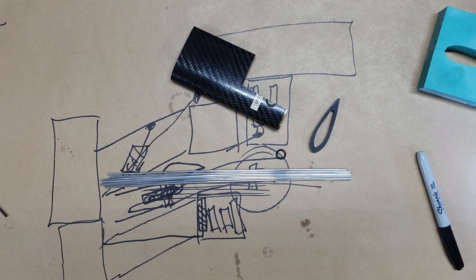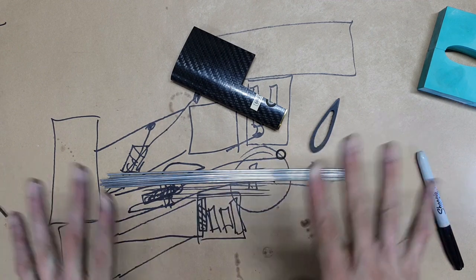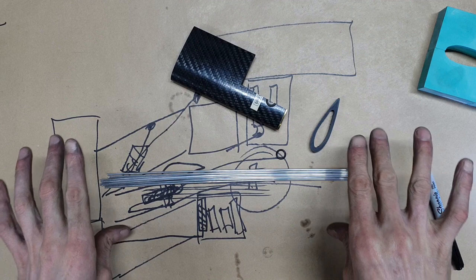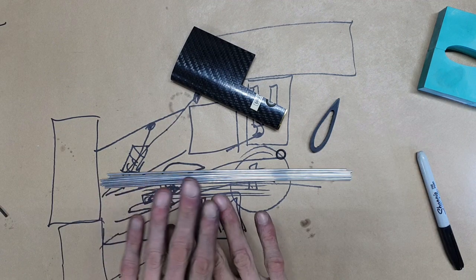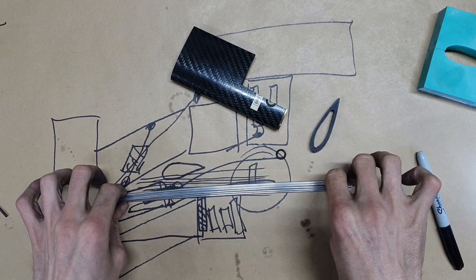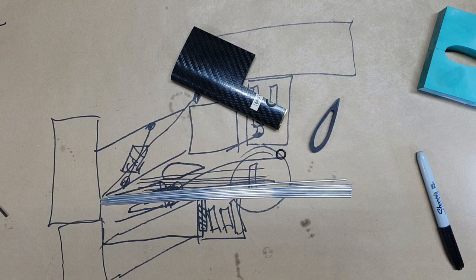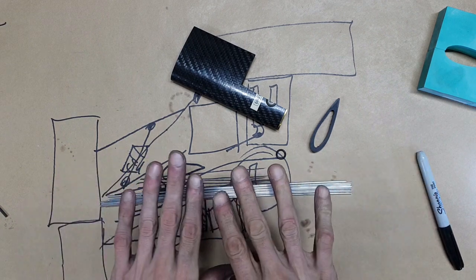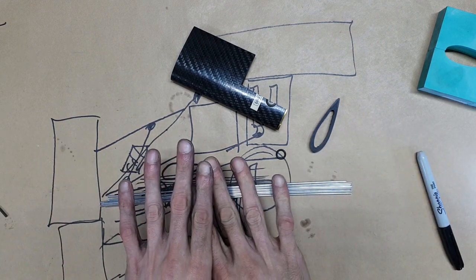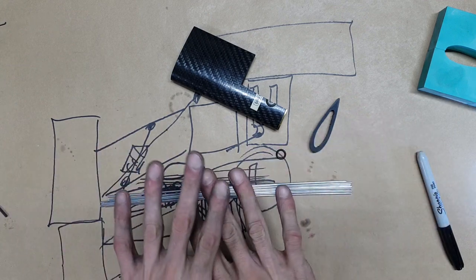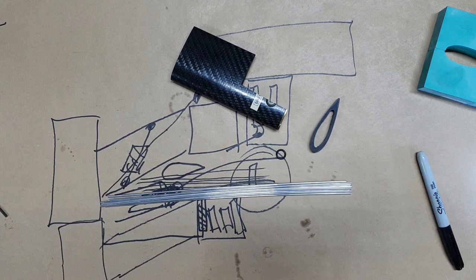Now, pre-preg carbon fiber is a sheet of carbon fiber which would start off as dry, but they vacuum impregnate a resin into it, which would be only approximately 35%, because you can control it so easily in factory conditions. You can wet the carbon fiber fabric, you can vacuum it off, you can make sure they're all wet, and you then freeze it, which prevents the epoxy resin from drying. So you can get a far higher carbon fiber to resin ratio with pre-preg.